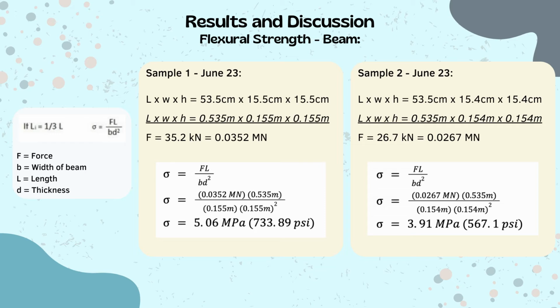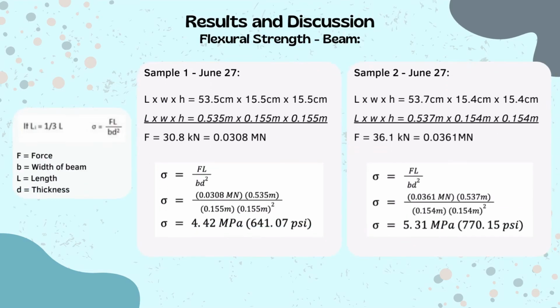While for the sample 2, we also have here their dimensions of 0.535 meters by 0.154 meters by 0.154 meter, and the force value of 0.0267 meganewton. So the flexural strength for sample 2 is 3.91 megapascal or 567.1 psi. For the second batch, we also have two samples conducted last June 27 and was tested last July 18, which had 21 days for curing.